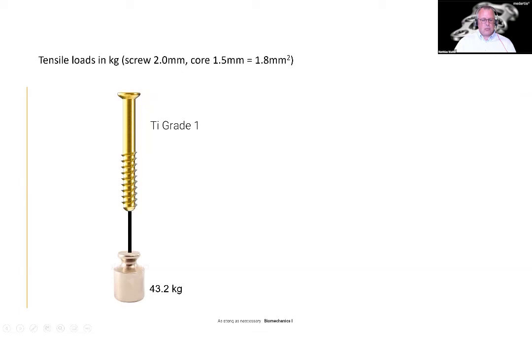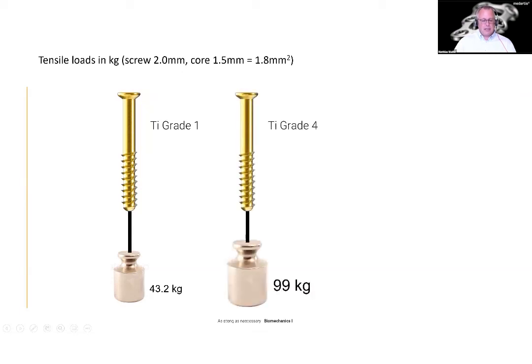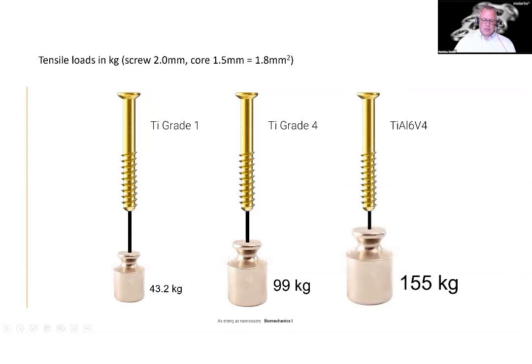If this screw, though, is made of titanium grade 4, it can already bear 99 kilos. And if we use the material that we are using, titanium aluminium vanadium, then, not surprisingly, it already takes 155 kilos, nearly four times as much as commercially pure titanium grade 1. So when this manufacturer produces a titanium implant, you always need to ask the question, which kind of titanium is actually used, to get a proper answer.